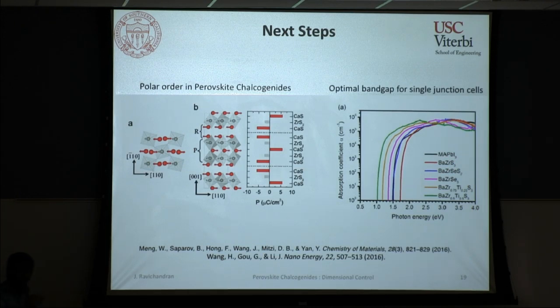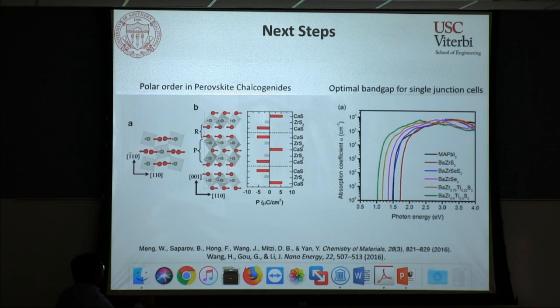One is, of course, trying to lower the band gap, where many people have tried to alloy these materials with titanium on the zirconium side, but since they have very different crystal structures, they tend to phase separate, so it's not a very good solution. The other option is to look for a polar order in these materials, which was interesting